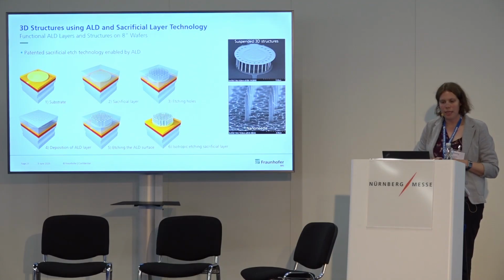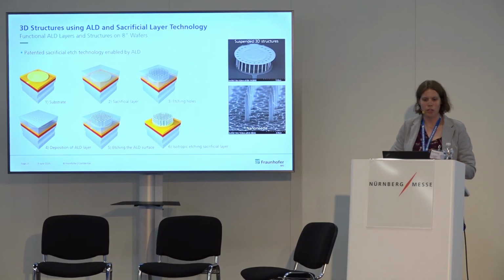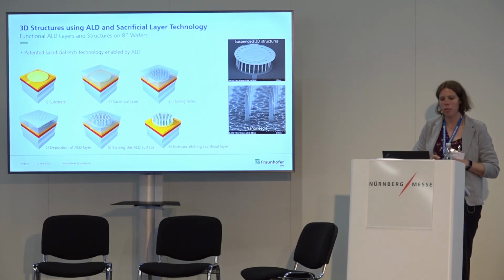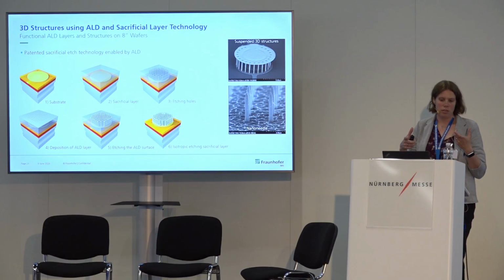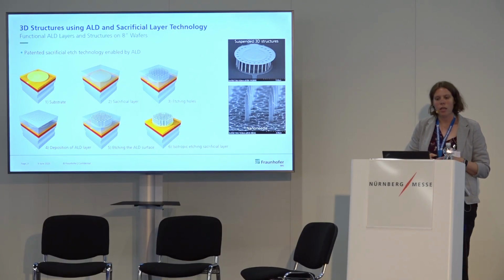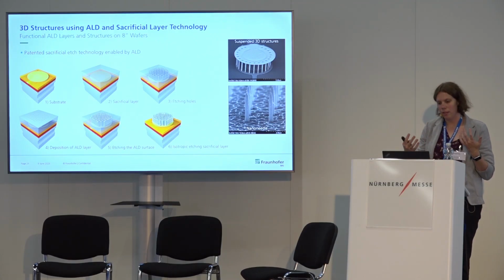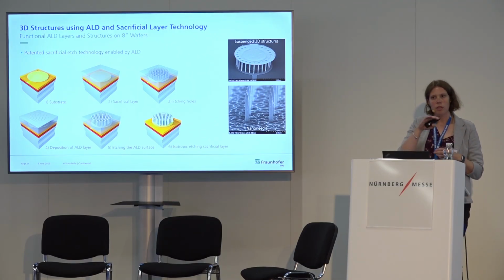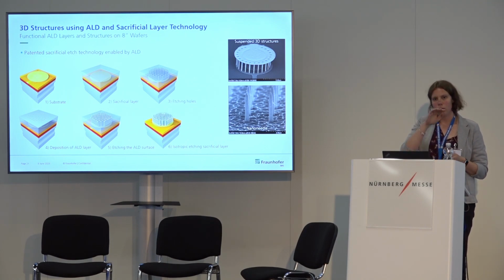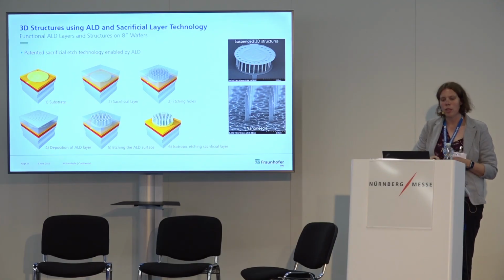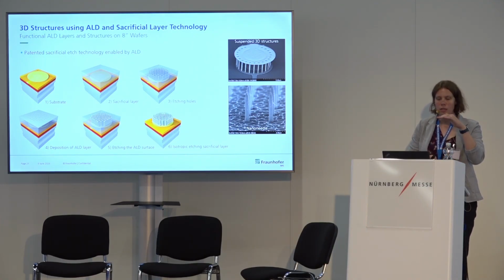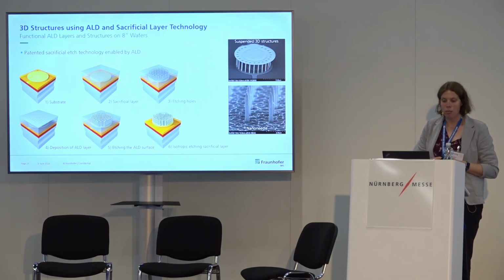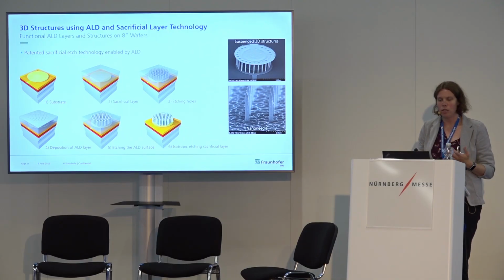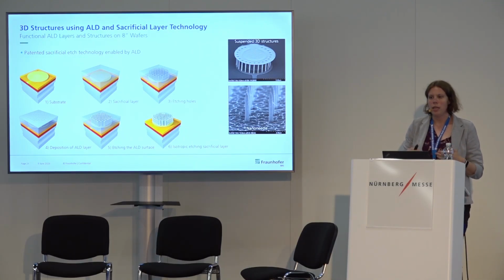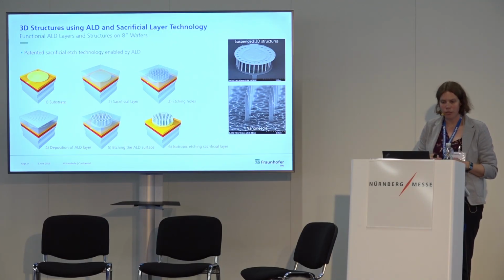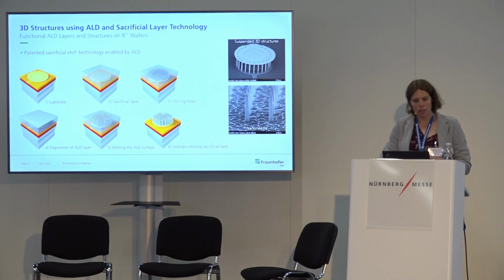So where do we use ALD? This is our sacrificial layer technology, which I already mentioned in the beginning. So how does it work? We start on a substrate, then we deposit a sacrificial layer. We are etching holes, for example, into the layer, or whatever other structure we want to produce. Then we deposit ALD, and because of the high conformity, ALD goes to the surface, but also inside all of these holes. Then we are etching the surface so that there is no ALD left. And then in the last step, we are using isotropic etching for removing the sacrificial layer, and only the ALD structures are left. On the right-hand side, you see two examples.